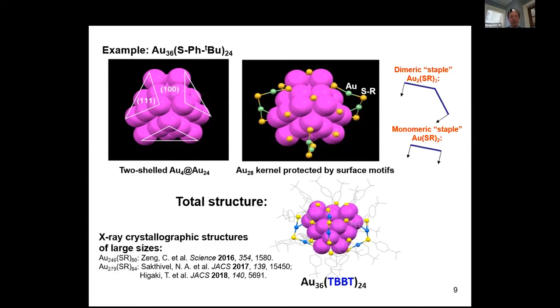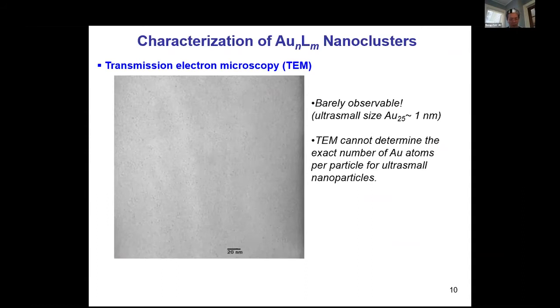And then, as I said, in recent years, my student and also some other groups were able to push up to much larger sizes, hundreds of atoms. So TEM is really important for nanoparticle research, and typically, we heavily rely on TEM to measure the particle size and the particle shape. But for ultra small nanoparticles like 1 or 2 nanometers in diameter, TEM is not so useful. I mean, you can still see them, but it's not really possible to precisely determine how many atoms per particle, what's on the particle surface, and what the bonding mode is, right?